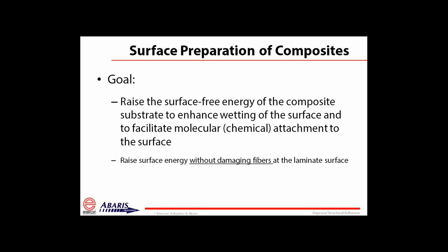We're not going to go into detail about the adhesives, but the surface free energy of the composite is going to react with the surface tension value of the liquid adhesive or the film adhesive that is being applied that will, as we'll demonstrate later, allow wetting on the surface to occur or will not allow wetting on that surface to occur. And raising that surface free energy on that surface is fundamental to getting the first step in your chemical attachment. Now, of course, we want to raise that surface energy without damaging fibers at the laminate surface.